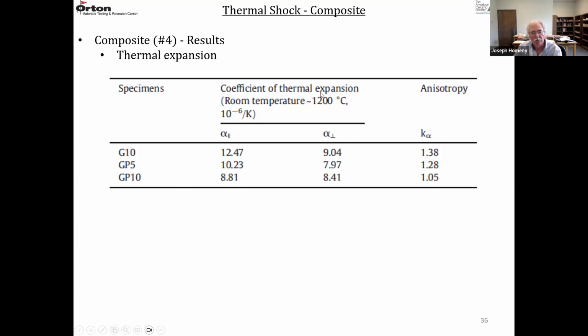So when you look at the coefficient of thermal expansion from room temperature to 1200 degrees C, this is parallel and perpendicular to the pressing direction. And then this is the ratio of the two. So G10 has the highest ratio, GP10 has the lowest ratio, and then GP5 is in between. So the addition of these pellets decreases the anisotropy, basically because they're crushing the large flakes of graphite into much smaller pieces.